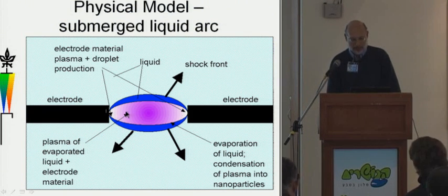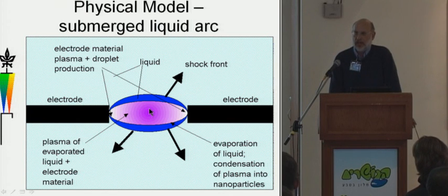Now, what we think is happening is the following. Clearly, we're producing a plasma. You could see it, and I could see it. The plasma consists of ionized material that came from either or both the electrodes and the liquid. In fact, if we look at the spectrum of these discharges, we see characteristic lines of atomic hydrogen, as well as OH, amongst other things. Those are easy to identify.